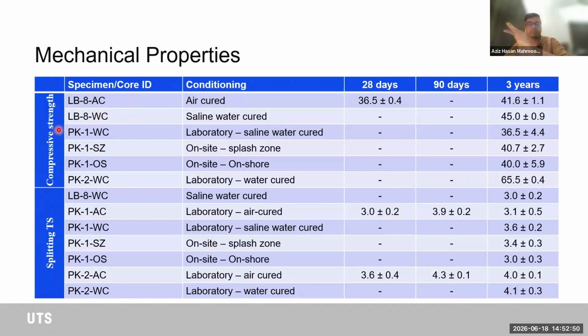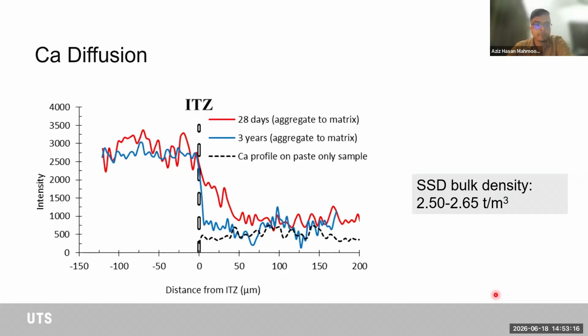And we also ran comprehensive testing. So I'm just demonstrating here the compressive strength and also the splitting tensile strength. So with the target 32 MPa, we could see that even after 3 years, the numbers looked very well, and we could see demonstration of continued geopolymerization and also development of strength of these units over time in the first 3 years.